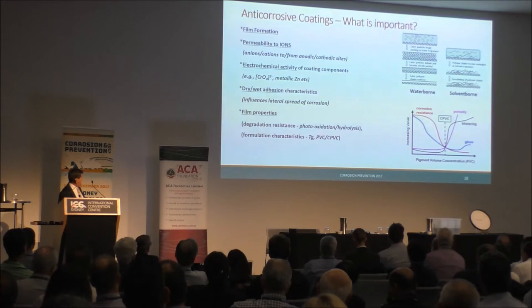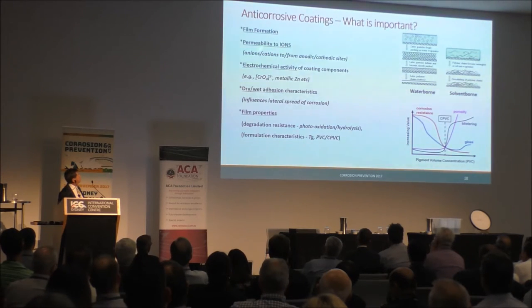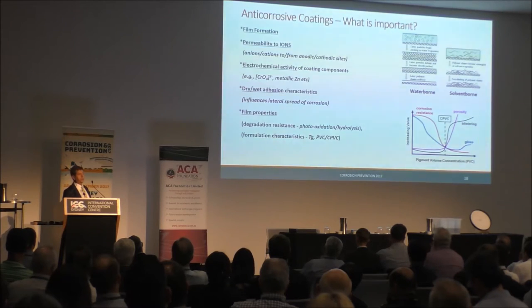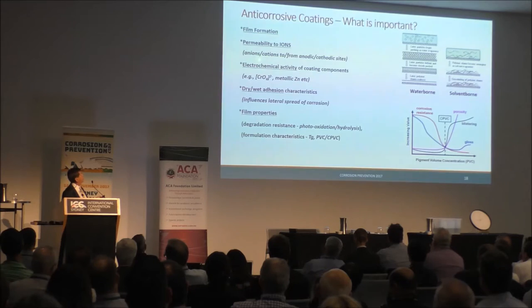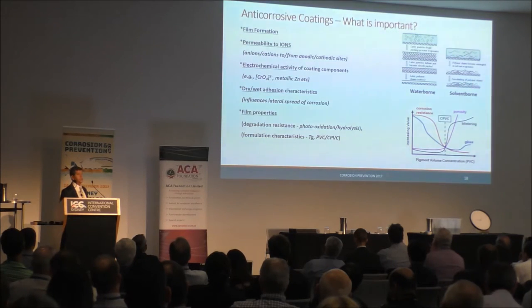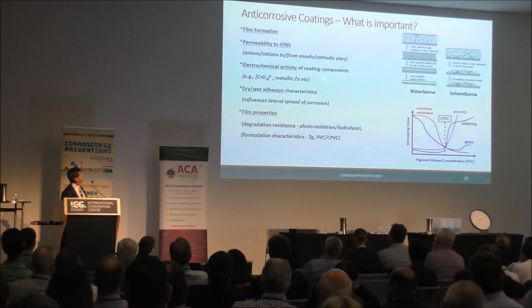So all things considered, what we find is that paints are permeable to oxygen and water, and the relative difference becomes the permeability characteristics of the corrosive ions. So even though oxygen and water can get through a coating, if you can control the rate at which ions permeate to anodic sites, you can use this effectively to prevent corrosion taking place. And the chemical activity of the components that are added, like oxidizing anions, chromates, and so on, allow you to design a paint that will work quite effectively.